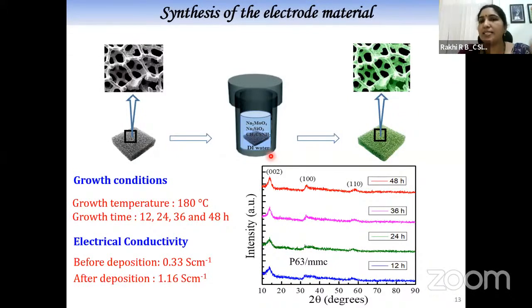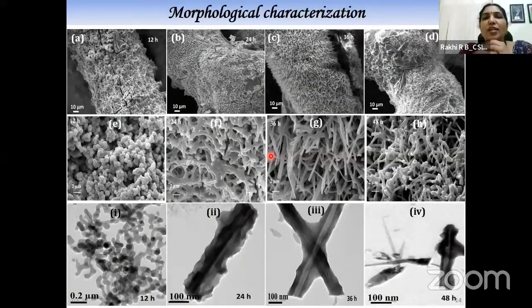Here again, all the samples had a crystallographic structure of hexagonal MoS2 with a space group of P63/mmc. Then what is the difference between the different growth condition samples? So these are the samples grown over the nickel foam, and when we zoom in, we can see like this. This is by SEM analysis. We have analyzed the morphology of the sample.